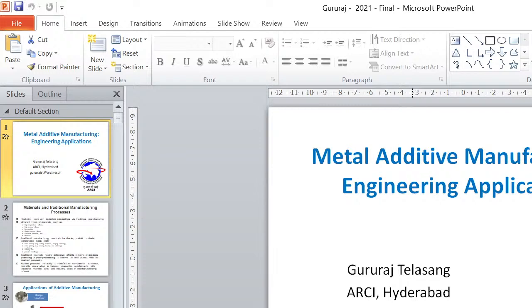Whenever I say I am selectively melting the powder and solidifying it, that is nothing but rapid solidification. So very high cooling rate. You will not get the equilibrium microstructure there. So you may end up with the entire component being very brittle and sometimes a different microstructure. That may not be suitable for your application. You may have to do heat treatment. So you need a material expert who will understand the microstructure and suggest a suitable heat treatment, right? Then you heat treat the component and use it for the required application after achieving the required properties, right? So we have those facilities. Then we have characterization. Sometimes you have to understand the material if you are developing the process for a new material. So all that facility. We have an atomizer also.